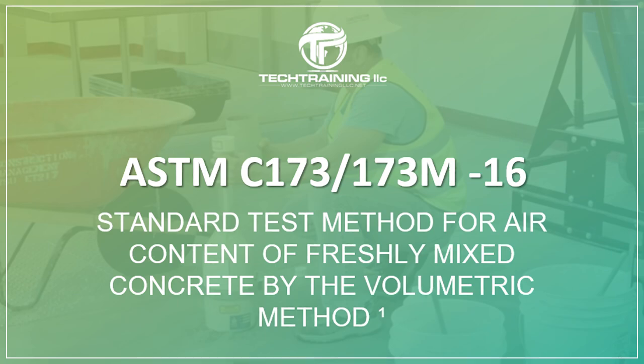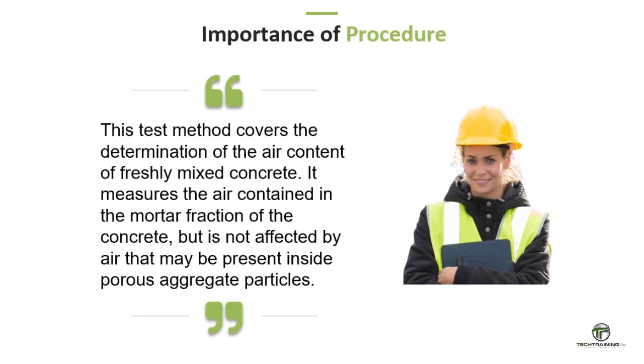ASTM C173 is the standard test method for air content of freshly mixed concrete by the volumetric method. This test method covers the determination of the air content of freshly mixed concrete containing any type of aggregate, whether it be dense, cellular, or lightweight. This test measures the air contained in the mortar fraction of the concrete, but is not affected by air that may be present inside porous aggregate particles.